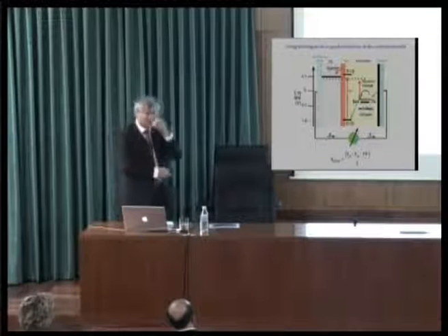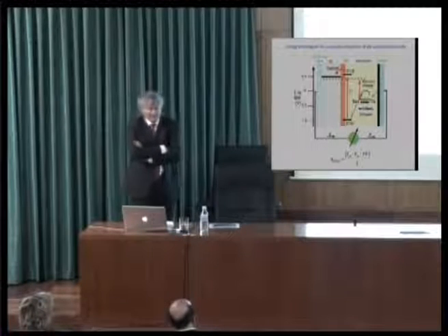nowadays we have been able to come up with some very promising solutions. Typically our solar cells have a VOC, or open circuit voltage, of 700 millivolts, or 750. If you're lucky, you get 800. But with this new couple, the cobalt couple, we get 920.